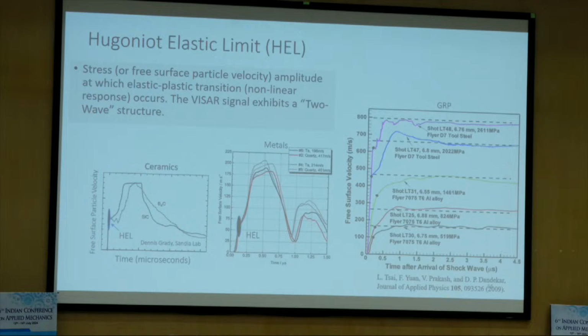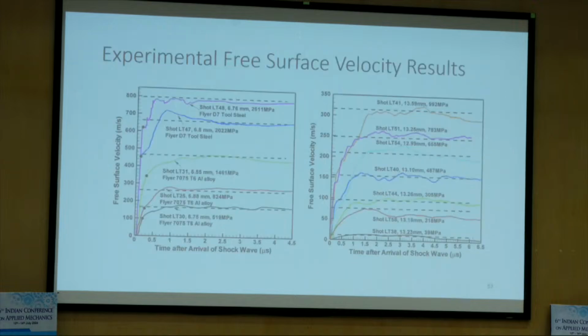So you expect dispersion, and that's what the plate impact test showed. Can we reproduce that using the so-called hyperelasticity model? We will see that. This is an experiment performed at Case Western University by Vikas Prakash with the funding from Army in 2009. So they did two tests, one thick composite, one thin composite. The thin composite is 6.8 millimeter, and the thick composite is double. And then they got this VISAR trace or signal, and we tried to model this.